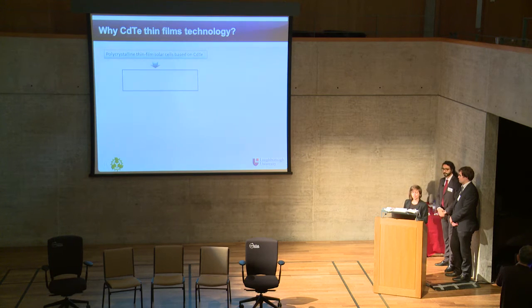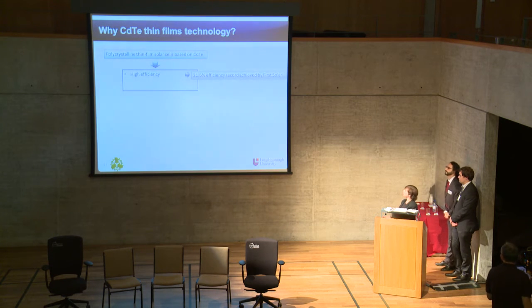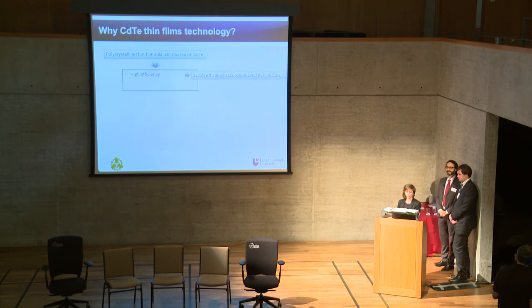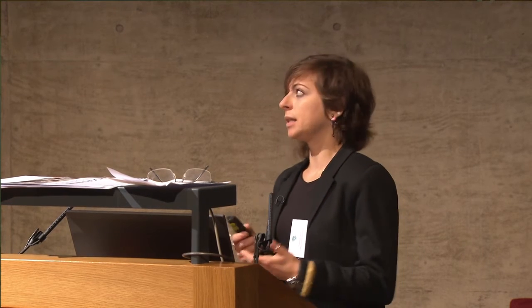So why cadmium telluride thin film technologies? We know that this process can achieve really high efficiency, and nowadays, First Solar has achieved a record efficiency of 21.5%, which is really close to what crystalline silicon technology reached, which is 25%. It's a long-term stable process with the potential for low-cost production. Because of cadmium telluride properties, in particular physical and optical properties, we can deposit a really thin layer of material, which is around 2 microns. So this means that with this kind of technology, we can save time, energy, and material.